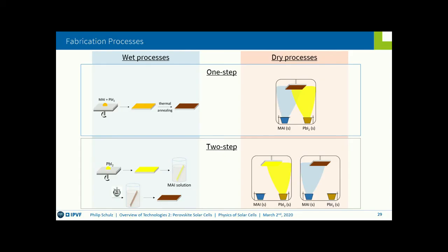An advantage for us was that we could use coating equipment that was already there and established in many groups. That's also why so many groups from the OPV community could enter the field readily. And you have relatively short processing times. In the dry processes, however, you get better reproducibility, usually better homogeneity over a larger area, and automation is better possible. The overall processing time, however, is much larger, and this plays into the cost of this vacuum process, or dry process.